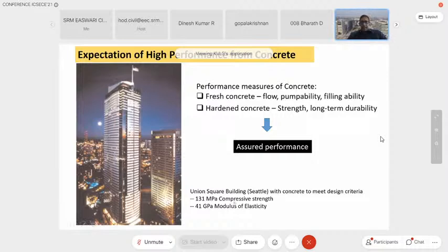Just to give you an idea, this is the Union Square building in Seattle, where of course a very high strength concrete was specified, but for the first time, they specified the modulus of elasticity of concrete. Now, this is not something that is very typical in specifications of concrete. The reason high modulus was specified independent of the strength was because if you increase the modulus of concrete, you can actually make the concrete stiffer, and the deflections of the building would be decreased. So this is one of those specification requirements that has been put in place for concrete.